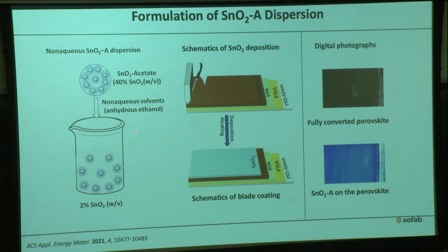For our initial testing, we selected ethanol as a test solvent, diluted tin oxide in ethanol, and deposited this tin oxide dispersion directly on top of the perovskite. This is the schematic of the deposition. Here it shows the fully converted perovskite, and after tin oxide deposition, the color changed to a shining color due to reflection.